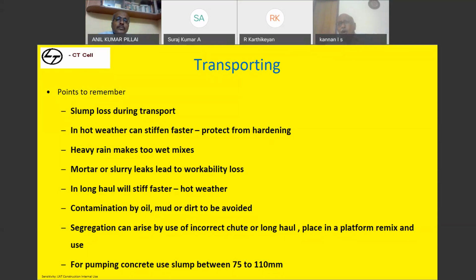Somebody will be adding water to push the concrete. So you should not retemper the material. Have a proper chute with a proper slope so that, as mixed, whatever concrete you receive from the truck, from the batching plant, needs to go inside the foundation without undergoing any corrections. For pumping concrete, normally 75 to 110 millimeters slump is more essential.